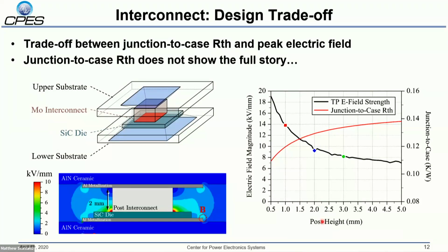So what this plot on the right is showing is the electric field intensity as a function of that post height, and also the junction to case thermal resistance as a function of post height. So you see these kind of competing physics. What's interesting to me is that the junction to case thermal resistance isn't the whole story. Once we get the heat to the case, we also have to exhaust it into the ambient.